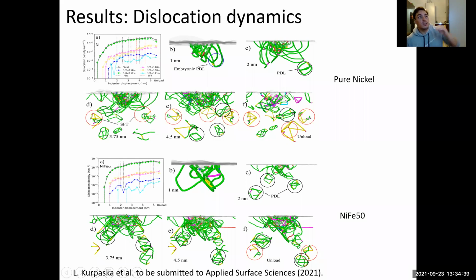For nickel, when you are doing an indentation at 1 nanometer depth, you have an embryonic prismatic dislocation loop that then, when you are going deeper, forms the prismatic dislocation loop. Then when you are going even deeper and deeper, you start seeing this pyramid, the so-called pyramidal shaped stacking fault tetrahedron. It looks like a pyramid, but maybe some people can say, no, it's not a pyramid, but it's a stacking fault tetrahedron. And they are formed mainly by the Hirth junctions. Then when you are going even deeper, you can nucleate more.